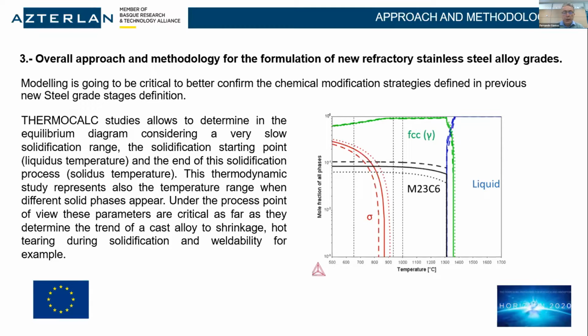It's quite critical. Let's say that, for example, from the thermodynamic study and the process point of view, these parameters are critical as far as they determine the trend of a cast alloy to shrinkage, for example, to hot-tearing, to solidification, and weldability. It's very important to take that into consideration.